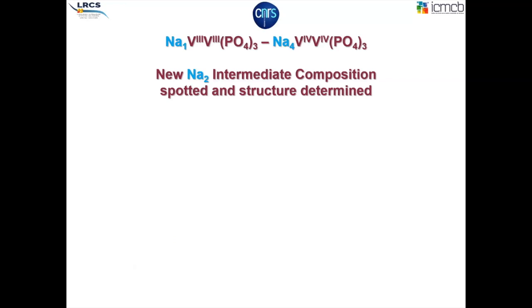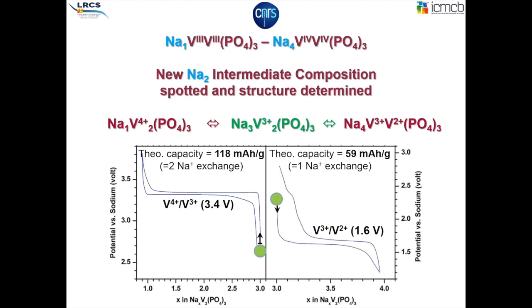I will focus my next 15 minutes on the NVP system, just to illustrate what we recently found on this very highly investigated system in the world. It looks very simple. NVP, as people prepare it, can be oxidized by sodium extraction at around 3.4 volts versus sodium towards Na1, but it can also be used reversibly as a negative electrode working at 1.6 volts versus sodium. This shows the feasibility of operating on more than one electron per vanadium, from Na1 to Na4, in a single NVP electrode that can play both sides, a negative or a positive side for a sodium ion battery.